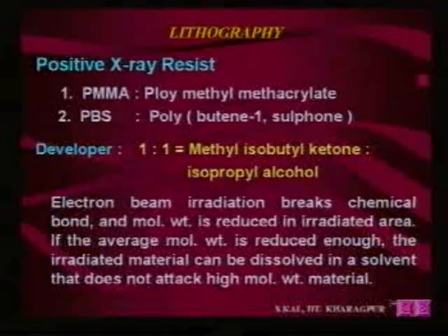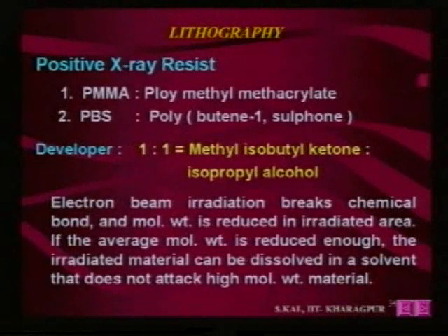And for this positive X-ray resist, the developer solution we use is 1:1 methyl isobutyl ketone and isopropyl alcohol. A 1:1 mixture we use for developing the positive X-ray resist.